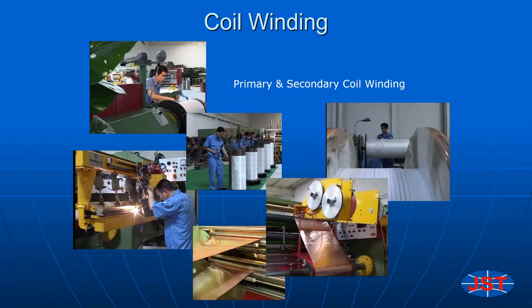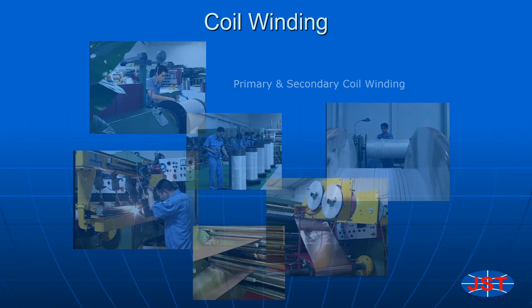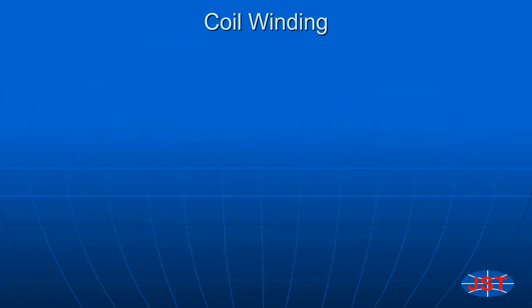What is not shown here is the preparation of the conductors. Prior to coil winding, except for the case of a conducting foil sheet, which is typically used in low voltage windings, the wire is wrapped with an absorptive crepe paper. Epoxy is drawn into the paper during casting, helping to ensure a void-free casting.